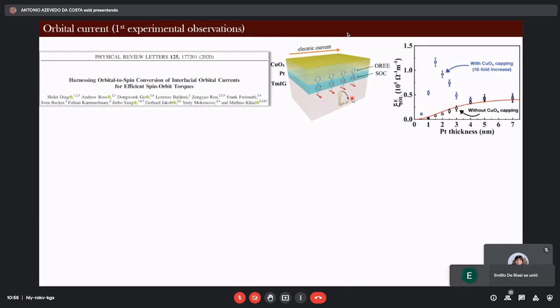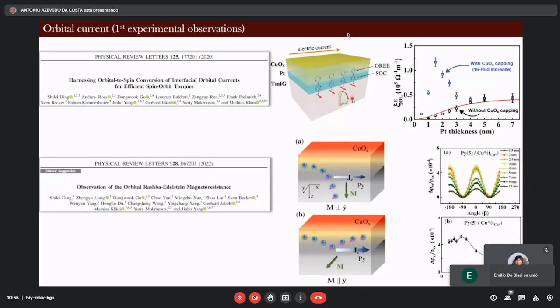And actually, this is an indirect way to measure the effect. And this year, a few months ago, this paper appeared, which is an editor's suggestion, in which they observed the orbital Rashba-Edelstein effect. In this case, at the interface between the copper oxide and platinum, they detected an orbital Rashba-Edelstein effect. They measured the anisotropic magnetoresistance, and also showed that it depends on the copper oxide, but it is also a very indirect way to measure this effect.